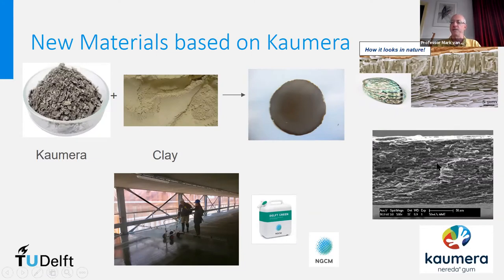So on the right-hand side, you see what we made, and you see how the shell looks under the microscope, and you see that the structure is very similar. And until now, with oil-based polymers, people tried to do it, they didn't manage. Whereas with these biopolymers, we actually quite simply managed to get the structures.